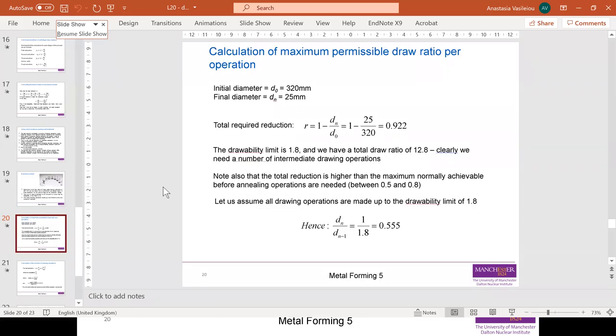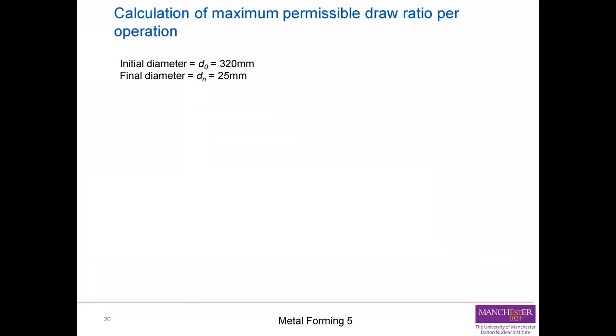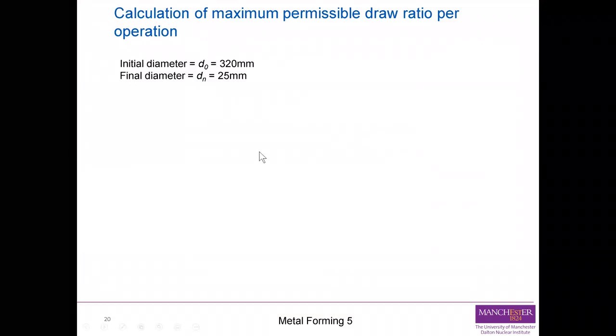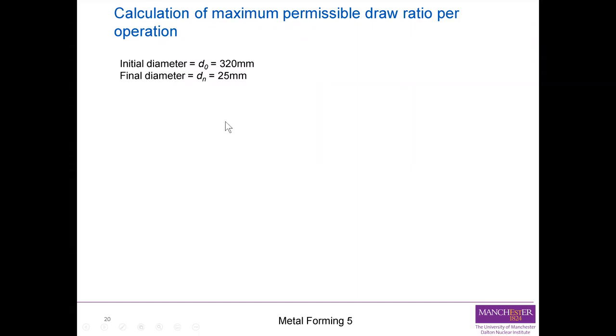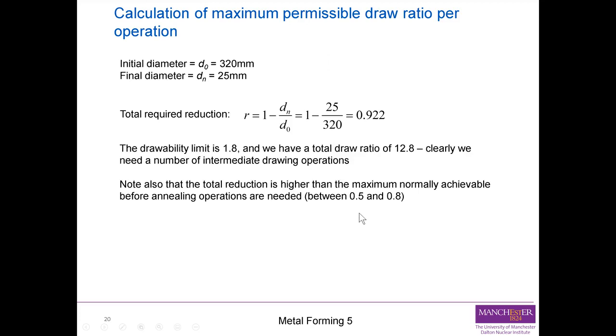So, starting with the calculation of the maximum permissible draw ratio per operation. We are given the initial diameter D naught equal to 320 millimeters, and final diameter Dn equal to 25 millimeters. So the total required reduction, as we said, this is the definition, is 1 minus Dn over D naught. By substituting the values, it is 1 minus 25 over 320, which equals 0.922. So we are given that the drawability limit is 1.8, and we have a total draw ratio of 12.8. This appears out of nowhere, but if you substitute, draw ratio is D naught over Dn. So 320 over 25 is 12.8.